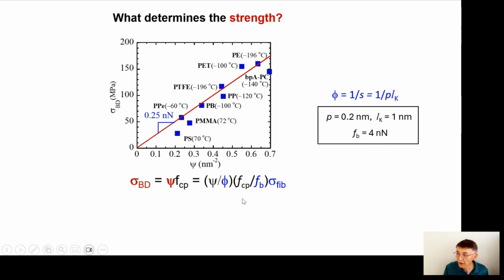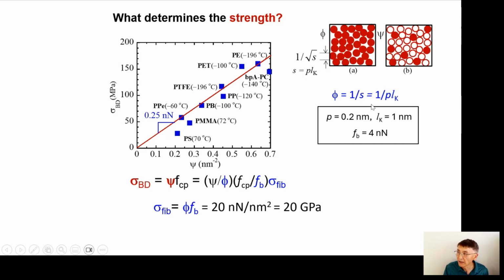And you can express my theory in a way that describes the fiber limit. I mentioned that people are really clever to make polymer fibers. The reason fibers are a clever product is they make all the chains aligned in the load-bearing direction, so that all the chemical covalent bonds are bearing the load. Unless you break the chains, you will not have failure. So at least in that idealized limit, indeed you can achieve strength as high as 20 gigapascals. So it's easy to compute and find out. So that's the fiber limit.